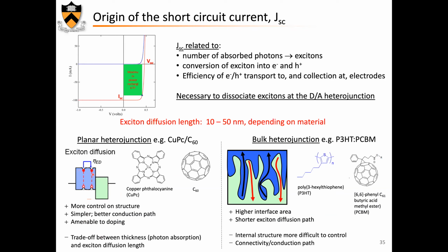The trade-off here is between the thickness and the exciton diffusion length. If you have too thick of a material, the excitons will not diffuse all the way to the interface, and you will lose most of them. If you have too thin of a film, then you will not absorb all the light that you should absorb, and therefore, a balance.